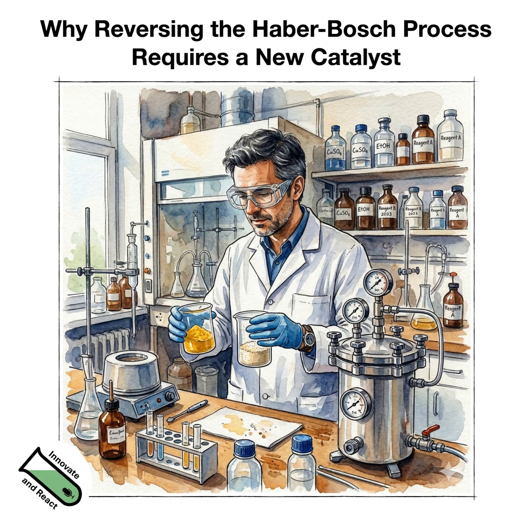Yes. So the iron is good at the reaction but likes to take up the nitrogen and be nitrided, and the cobalt is not as good in the reaction but doesn't form the nitrides. In combination you get a higher activity because no nitrides are formed, but still the iron can perform the reaction.